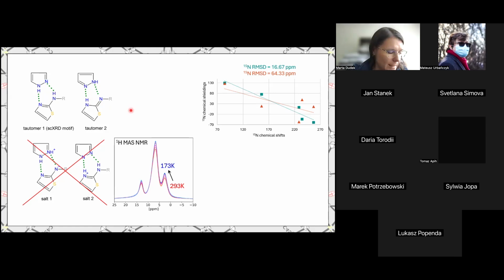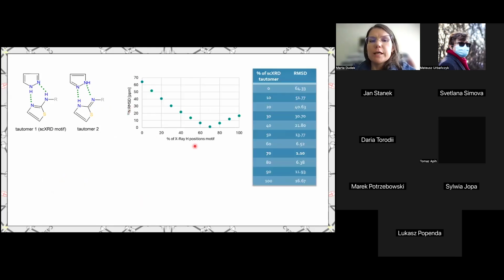So we then decided to calculate weighted averages of the chemical shifts using different percentages of tautomer 1 and tautomer 2, and calculated RMSD values for those averaged structures. What you see here is a plot of the dependence of the percentage of the X-ray H position motif against nitrogen-15 RMSD. And we have a very nice minimum here, which is definitely below the 6 ppm cutoff line. This structure corresponds to 70% of one tautomer and 30% of the second tautomer.